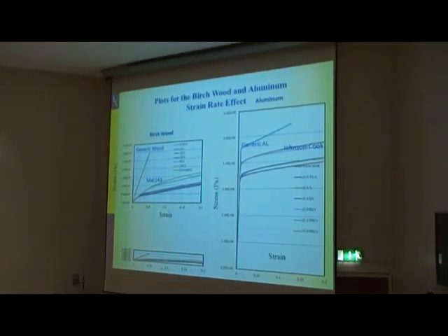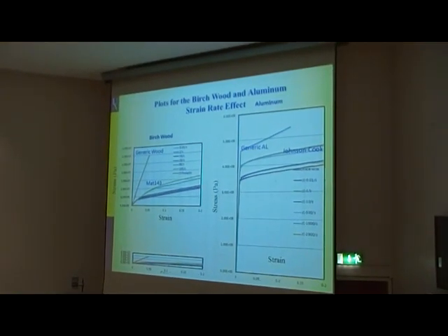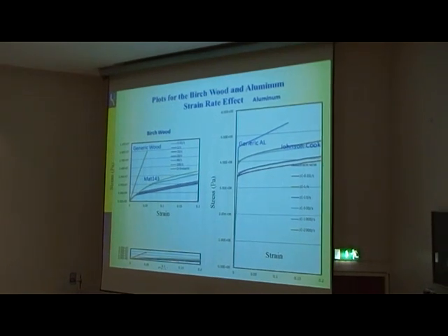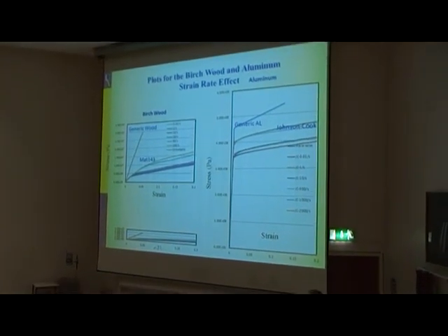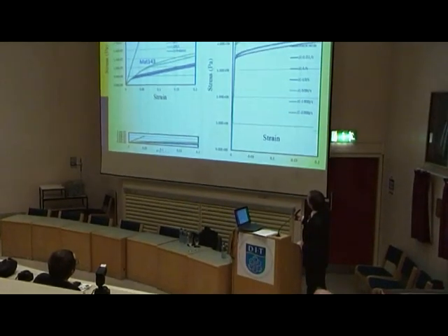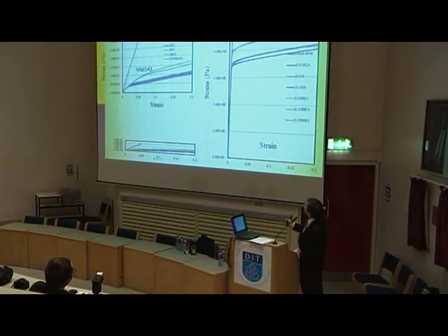Again, if you look into the stress strain curves of different models that we used, like Johnson-Cook, or bilinear, or this tabulated, together with the material model used for the wood, generic orthotropic model or material 143, if you squash this to this level to show the same vertical scale, you can see how weak the tree is in comparison with aluminum.